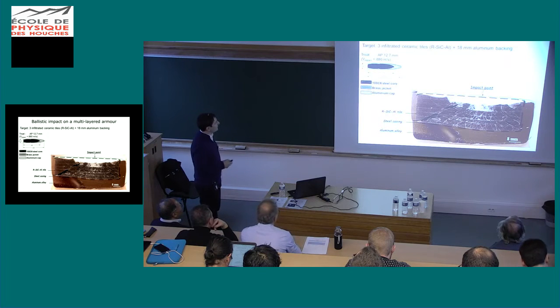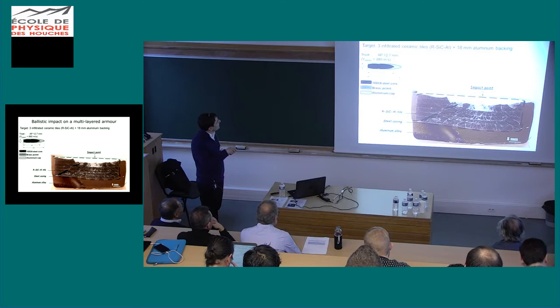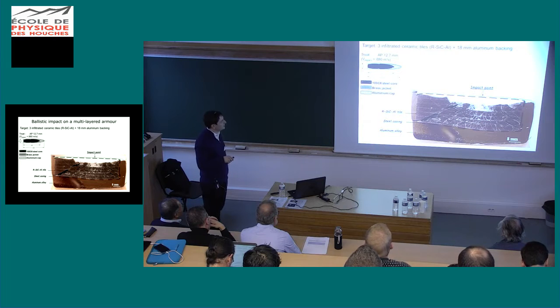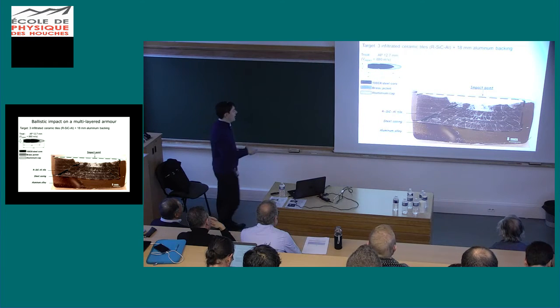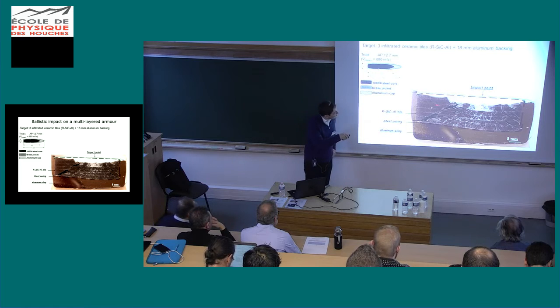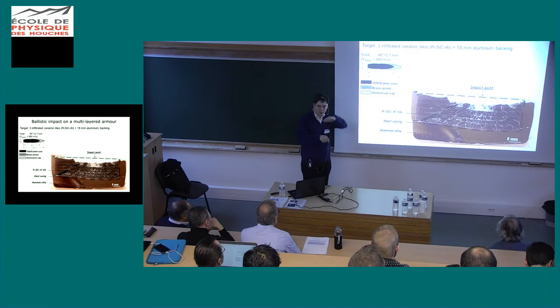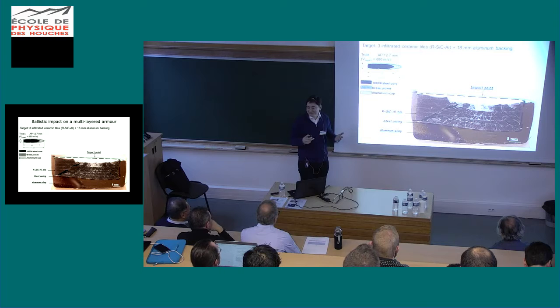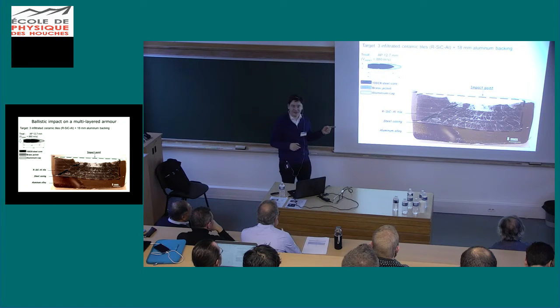Another example, a very interesting example. In this example, a target, you can see here a cut view of the target, was impacted with an armor piercing projectile, 12.7 millimeter diameter caliber, at an impact velocity of 880 meters per second. And what is interesting is it seems that the target is deformed, but not eroded. It's very strange, but it is made of ceramic. Okay, so why?